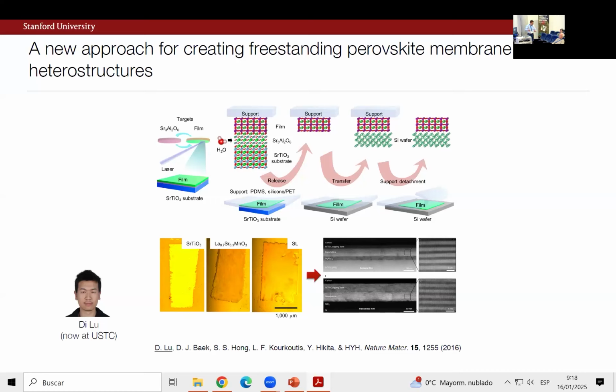The second point that we and others are starting to utilize is that the advantage of this is you're growing generally on substrates with lattice constants and environments that are really optimized for the materials you want to study. And so this was what Di shows here, the growth of strontium titanate, lanthanum manganite superlattices that have been lifted off and transferred. Okay.